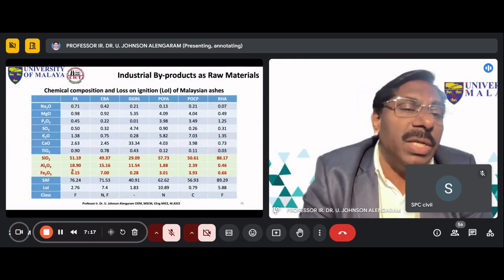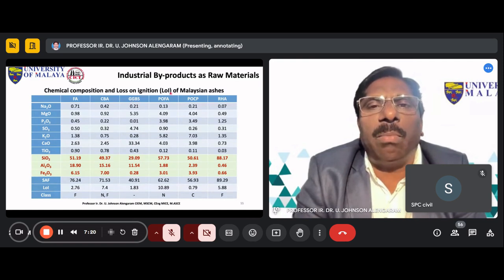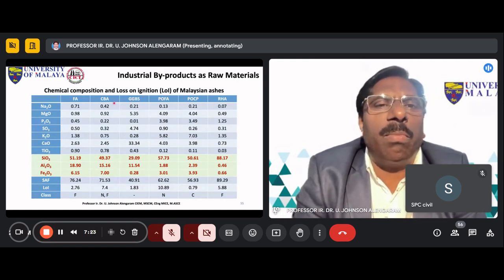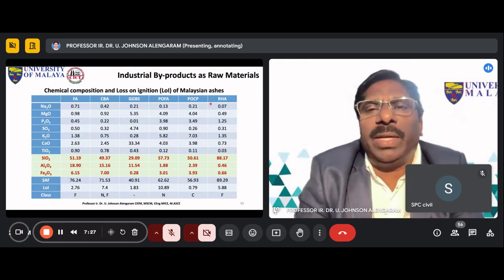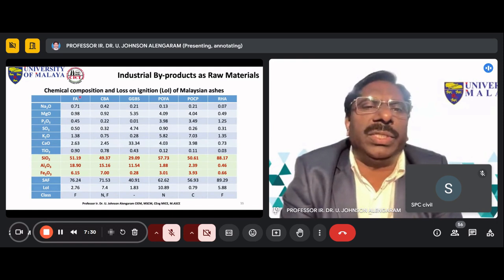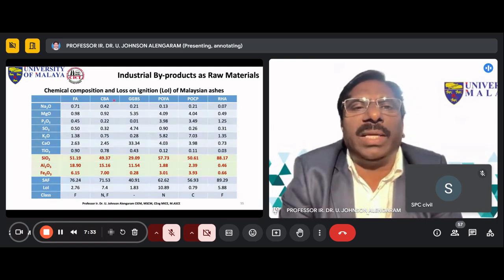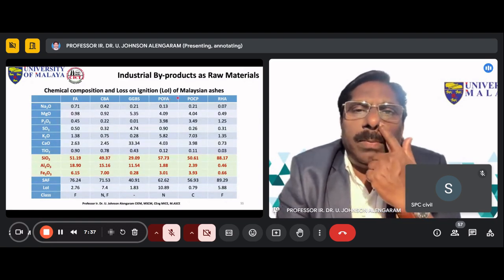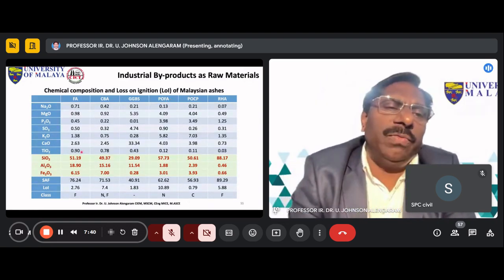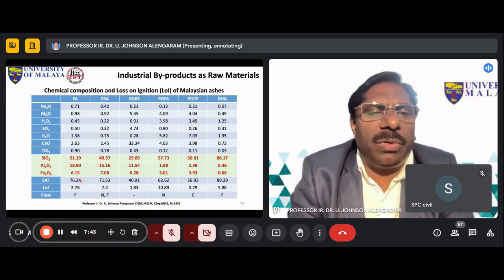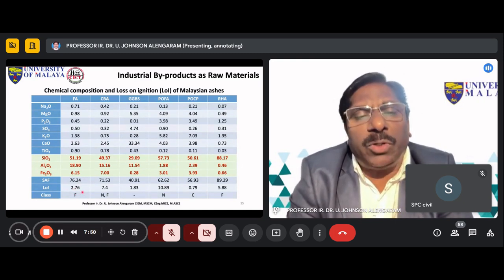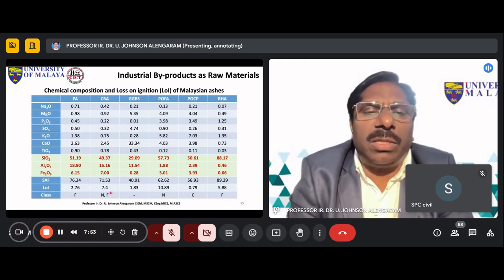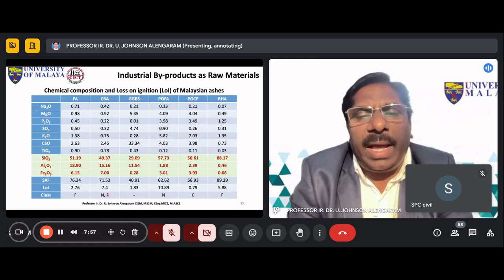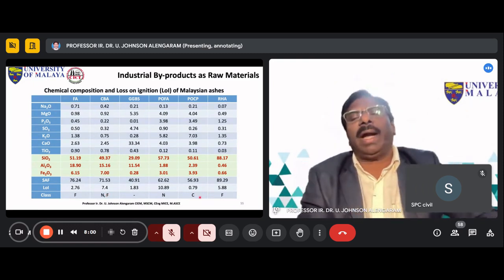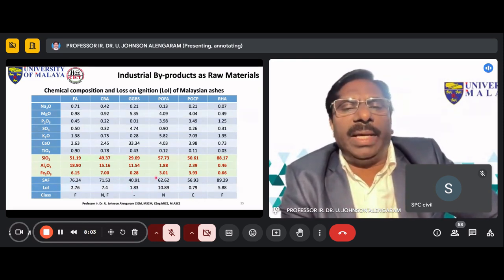At the same time, they should be resilient, because if you look into this GGBS, palm oil fuel ash, palm oil clinker powder, rice husk ash, coal bottom ash, and fly ash, these are some of the materials that are available. Some are traditional. This has become traditional, but the other things are non-traditional: palm oil fuel ash, palm oil clinker powder, rice husk ash. If you look into the silica, alumina, iron content, I'm sure this one, about 76%, falls under class F material or pozzolanic. This one is class C material. So these are the pozzolanic. Some of them fall under class C, class N and F. So based on the calcium content and silica content, they can be classified and utilized.